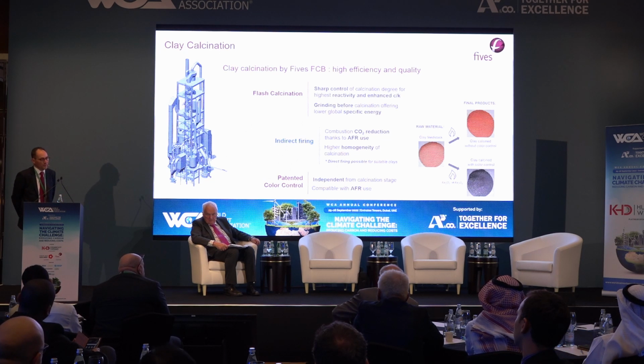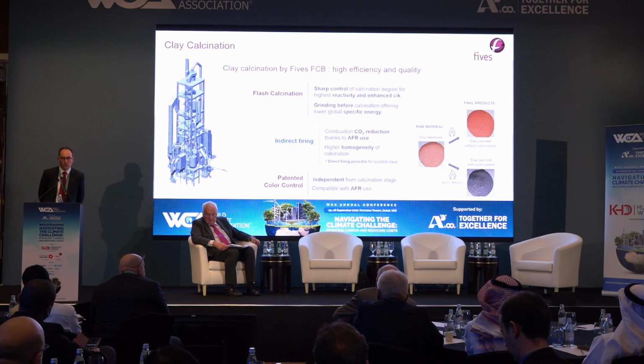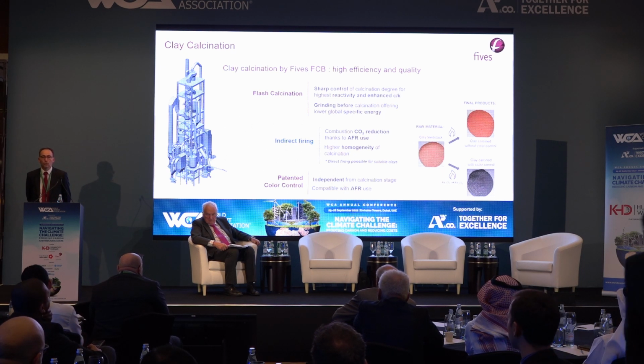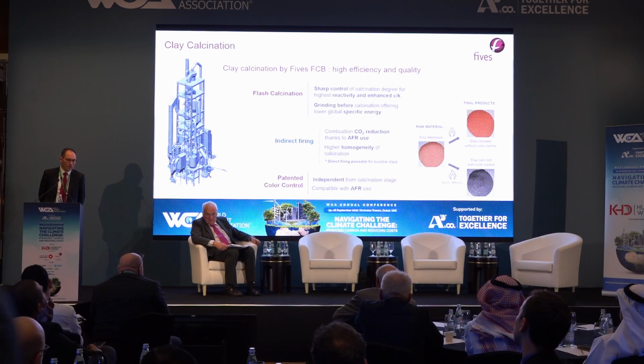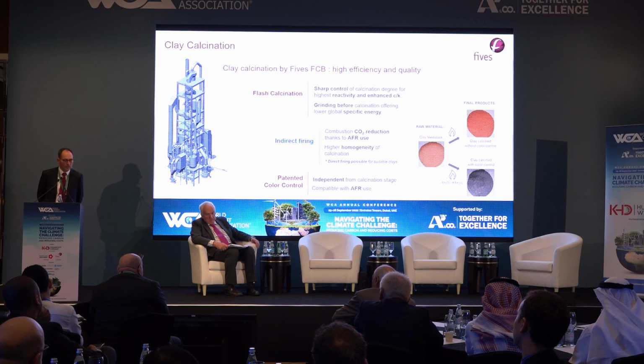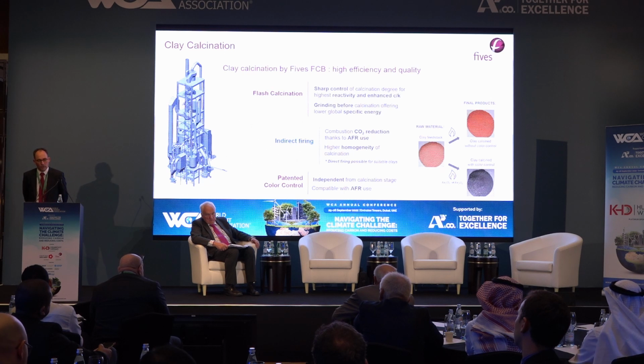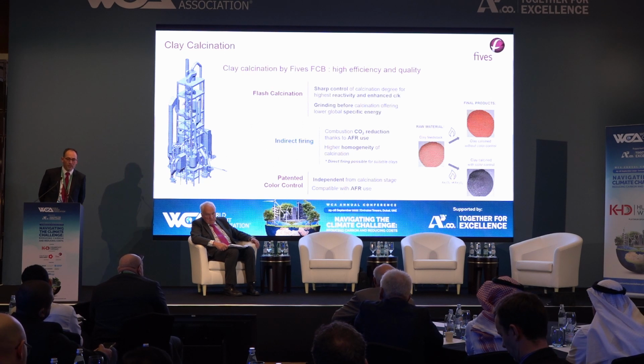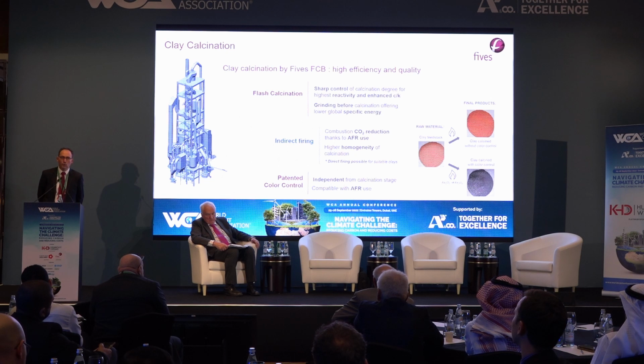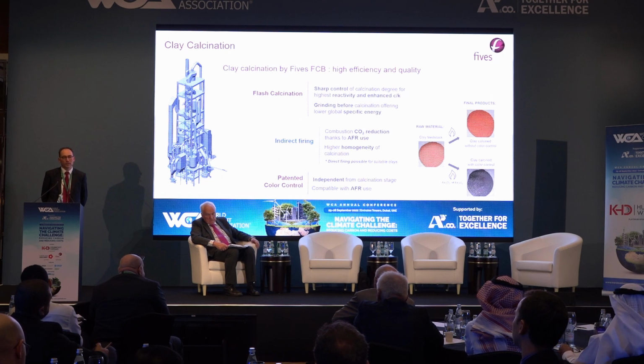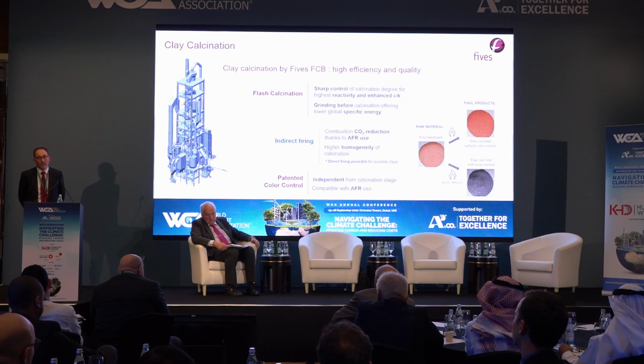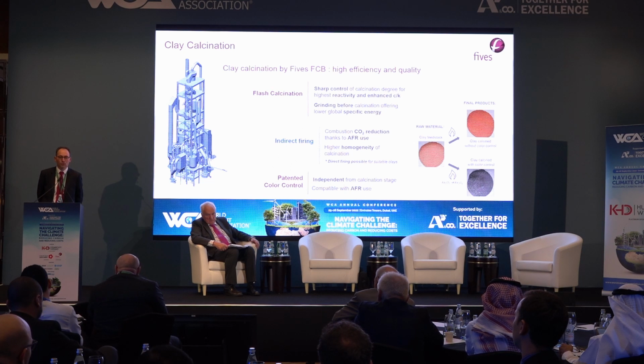So what we have done in FCB is to rather give a preference to the flash calcination in comparison to calcination in a rotary kiln, to have a sharpest control of the calcination degree, and thus doing grinding before calcination. One of the significant advantages, we have heard yesterday that we have huge amount of clay available worldwide for calcination and to introduce in our cement. But clay has different qualities. Some are more appropriate to calcination and to do cement.